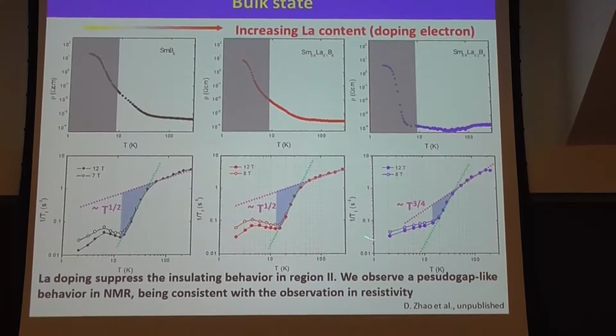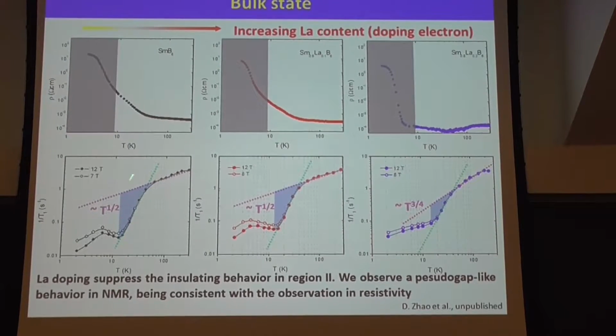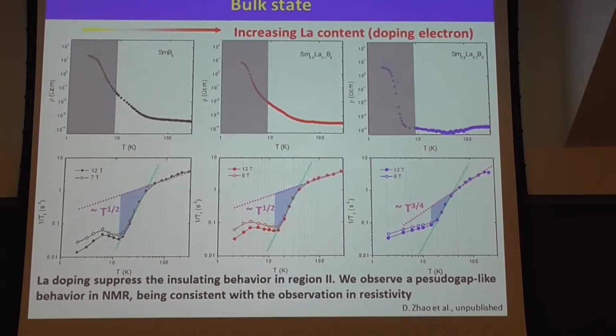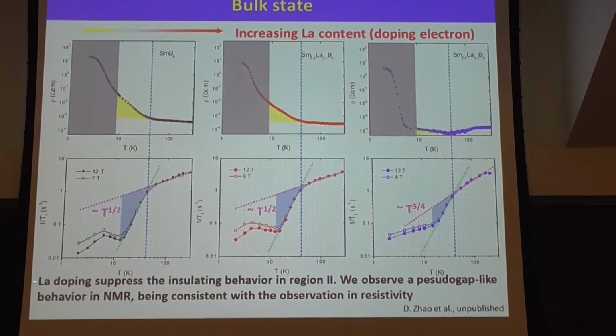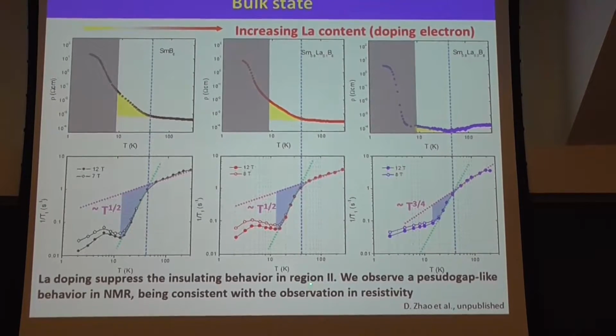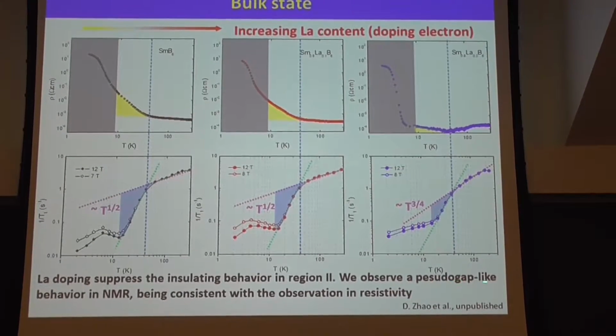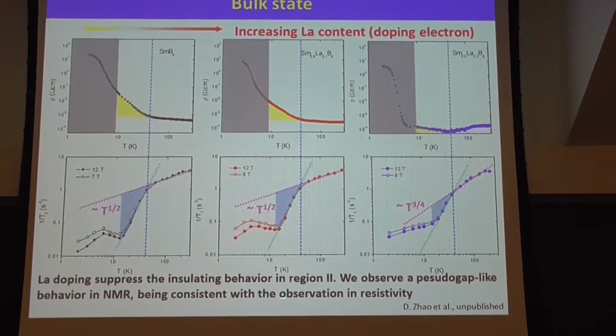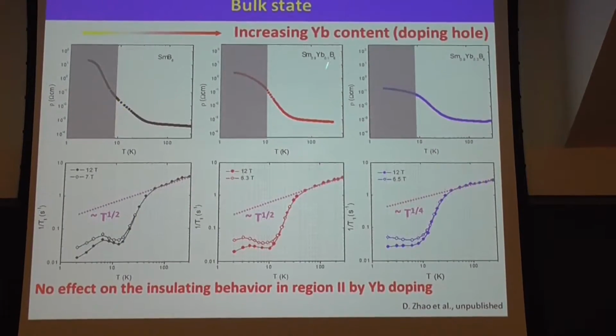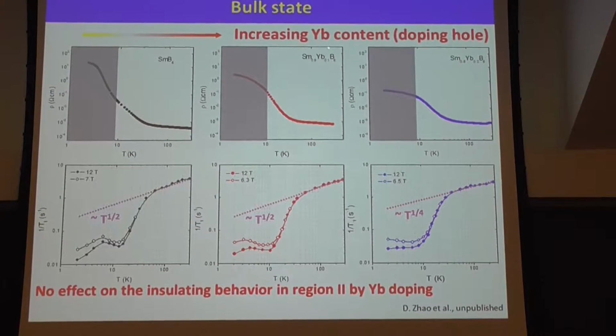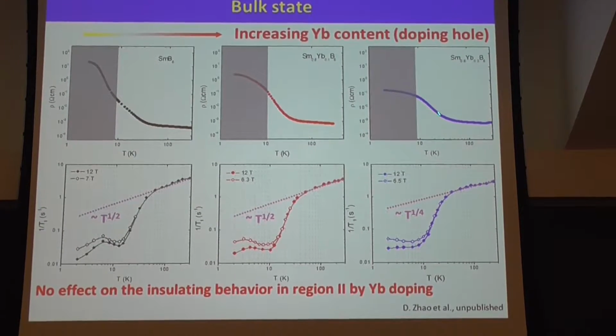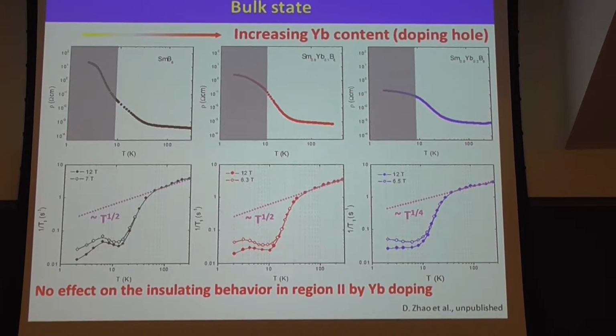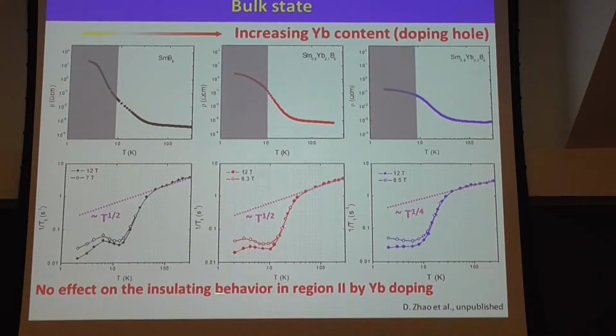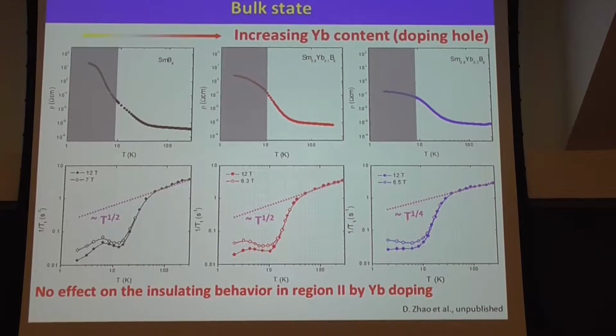Okay, this is from the NMR, this is the macro area showing the gap magnitude. Anyway, lanthanum doping suppresses insulating behavior in region 2. We observe the hybridization gap-like behavior in the NMR being consistent with the observation in the resistivity. And also we have this sample using ytterbium. This ytterbium is hole doping. You can see hole doping doesn't change this insulating behavior. Also, the NMR data shows that the hybridization gap almost doesn't change. This means there's no effect on the insulating behavior in region 2 from ytterbium doping. Okay?